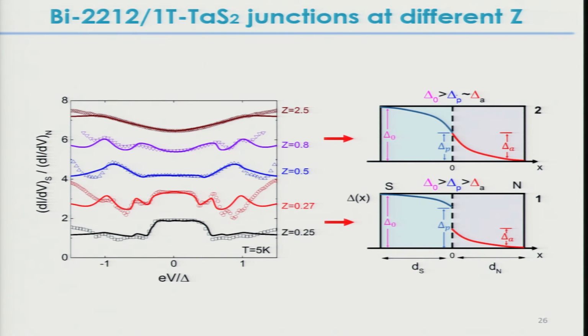And eventually, as we go up to lower transparencies, this gap closes here, and it becomes more or less continuous. But there's still a proximity effect into the superconductor. So these curves are showing that this Andreev reflection feature disappears as you go up to less transparency. I'll make the remark that this is a rather big gap, 20 millivolts. It's half the gap of Bisco.